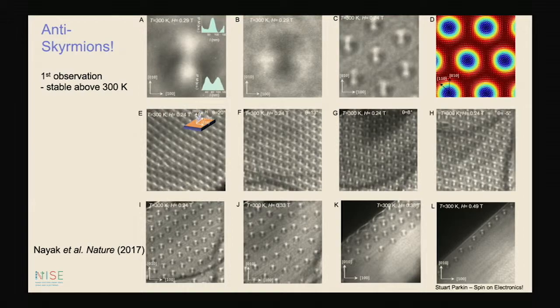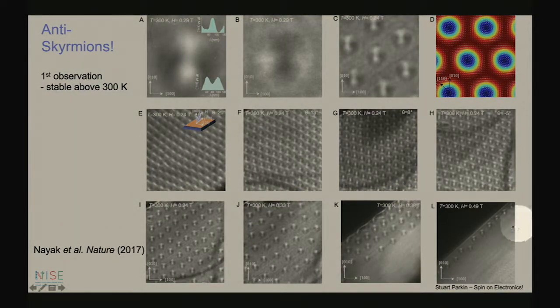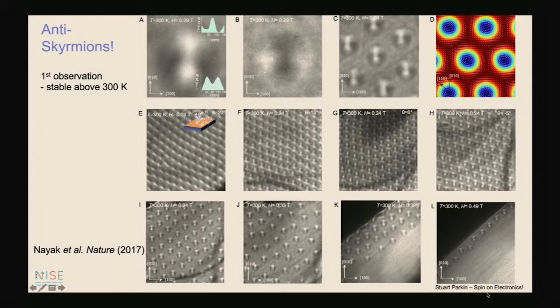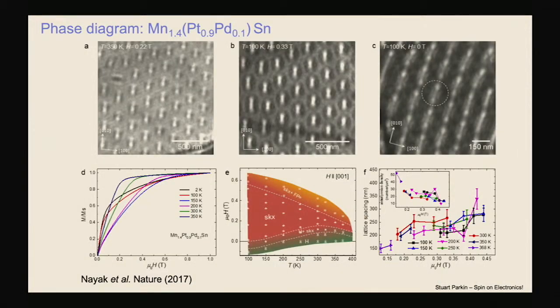And you can see here on the edge of this device, a row of anti-skyrmions. And so as you increase the field, you start to eliminate the anti-skyrmions, but depending upon the thickness of this lamella, there's a different phase stability. I want to come back to that. This is just showing you this. Now, by the way, this material we're looking at is a little bit complicated.